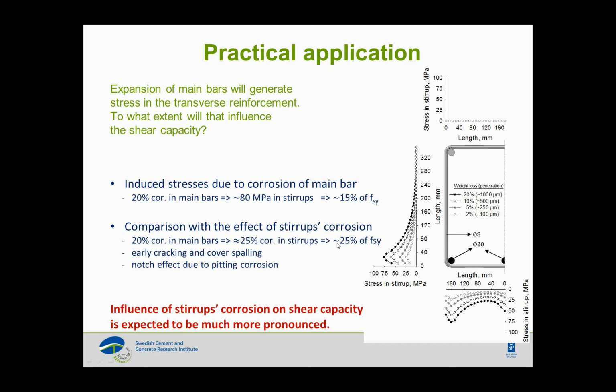And in addition to that, you get early cracking due to corrosion of stirrups. You get early cover spalling due to corrosion of stirrups, and on top of everything else, you have this notch effect due to pitting corrosion, in case you have pitting corrosion. Putting all these together and comparing these two cases, we get an impression that even though corrosion of a main bar induces some stresses in the stirrups, that is not as important as corrosion in the stirrups directly.